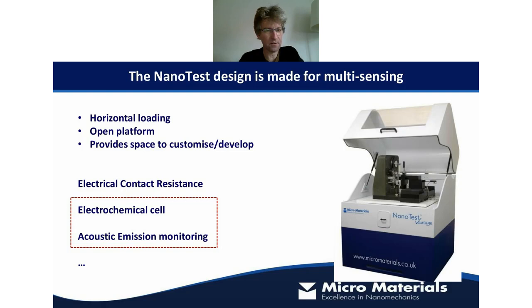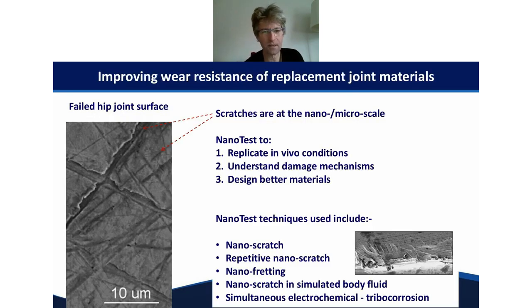So as I say, I'll focus this time more on electrochemistry and acoustic emission, just a couple of quick examples with each. So if we think about another situation where electrochemistry could be quite important, this is an SEM image on the left of a so-called retrieved hip prosthesis. This one has failed, and you can see the surface is covered by a large array of different scratches, and it's very complicated to try and untangle that and understand what was going on in terms of that